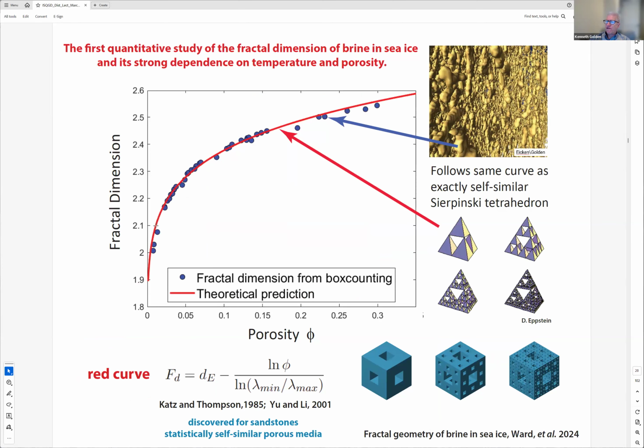Here, this red curve is the exact result for three-dimensional, exactly self-similar fractals, such as the Sierpinski tetrahedron, or there's the 2D version, the Sierpinski triangle, of the fractal dimension as a function of the porosity as you go through the different levels, say of the Sierpinski triangle. But here's our data, and it fell right on that curve, which I just didn't expect, and we didn't believe it for a while, and it took quite a while to really sort through all this and actually believe it because it's so beautiful.